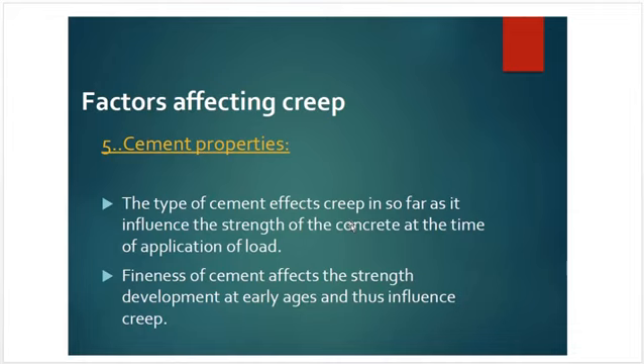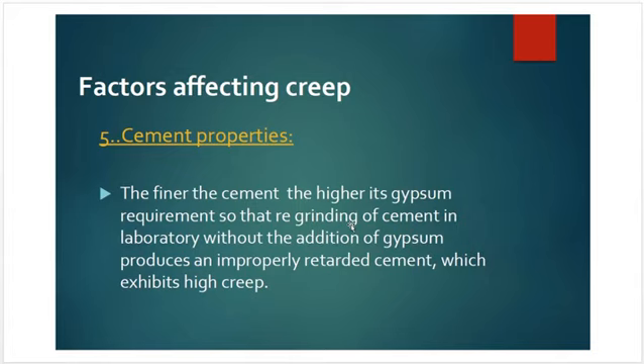The type of cement affects creep insofar as it influences the strength of the concrete at the time of application of load. The fineness of cement affects strength development at early age and thus influences creep. Higher fineness of cement leads to higher gypsum requirement. Re-grinding of cement in the laboratory without addition of gypsum produces an improperly retarded cement which exhibits higher creep.